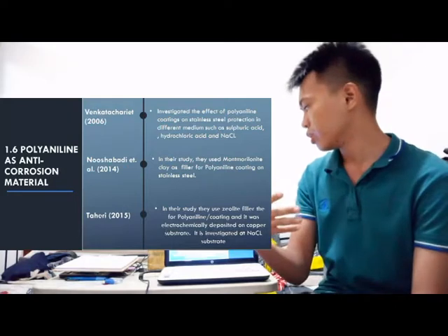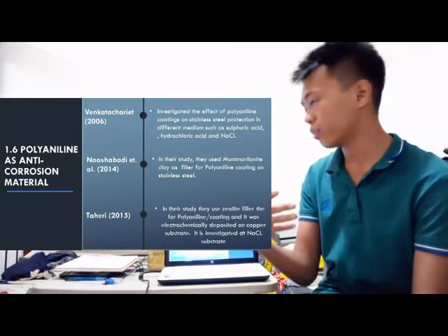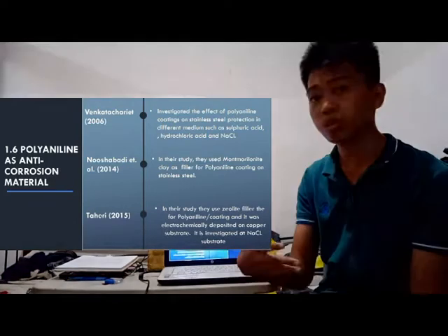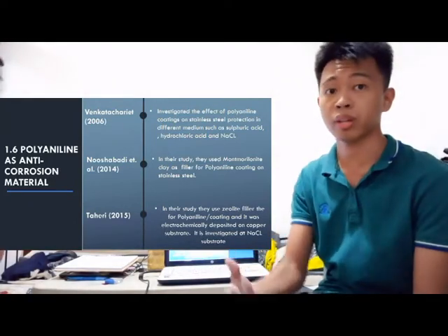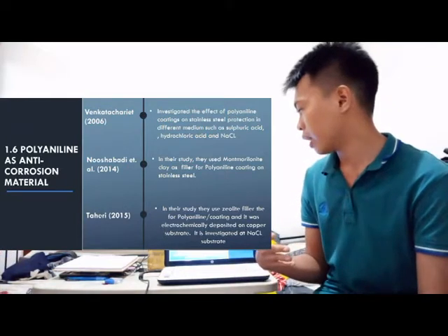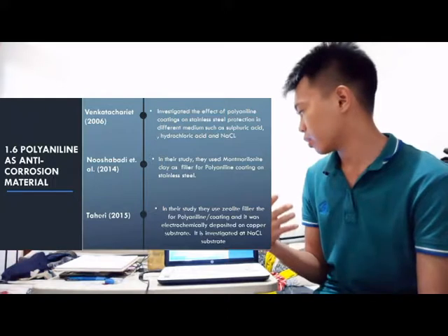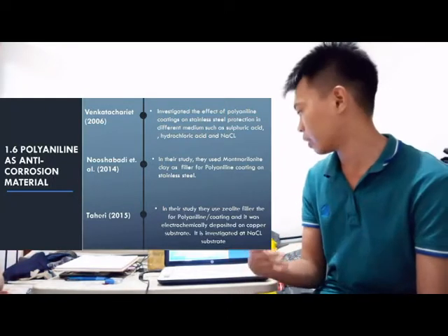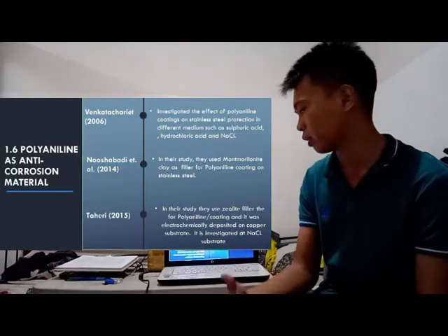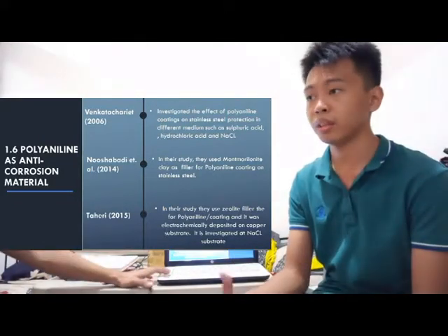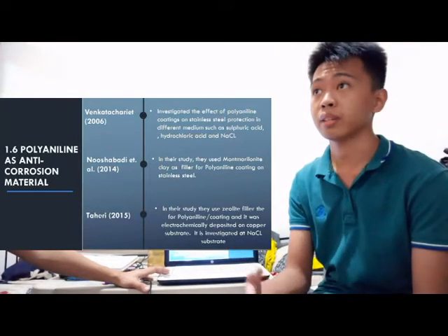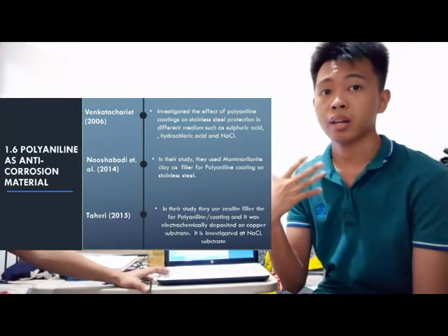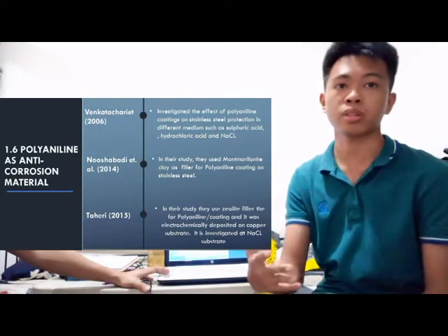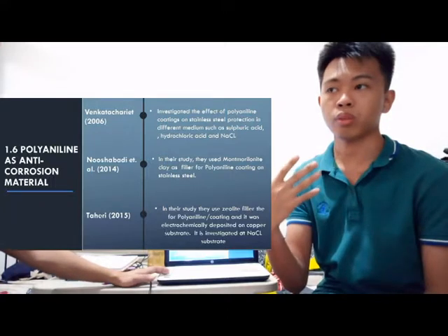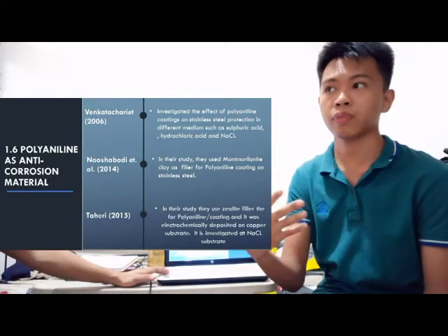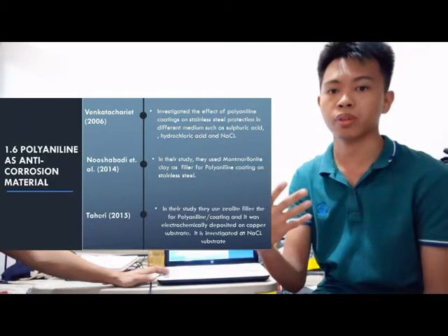of the corrosive medium. In the year 2015, an author named Taheri and his colleagues introduced zeolite as a filler for anti-corrosion material. They used zeolite, and for the matrix they also used polyaniline. It was electrochemically deposited on a copper substrate under galvanostatic condition, and the zeolite presence generally increases the tortuosity of the diffusion pathways. What do you mean by tortuosity? It is something related to a curved path, and this curved path will generate delay in transport of the corrosive medium from the substrate.